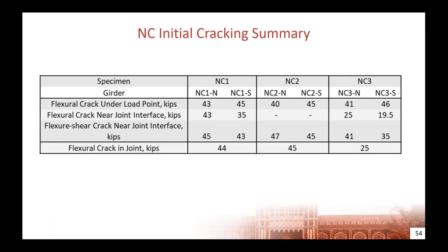If we compare these two joint details, we can look at their cracking performance and their ultimate load performance. For cracking of our new construction joint, we saw our first flexural crack somewhere in the 40 to 45 kip load range. We saw flexural cracks near the joint interface somewhere in that same range, and then flexural shear cracks at the joint interface at about that 40 to 45 kip range as well. We first started seeing flexural cracks in the joint at about 45 kips for specimens 1 and 2, which were not tested in positive moment first.